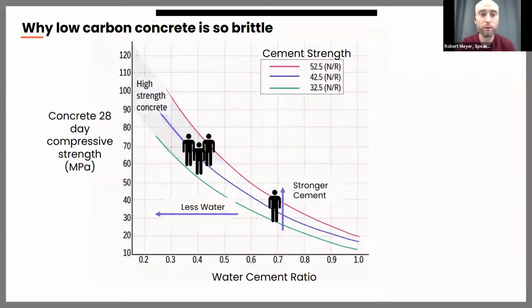Okay, so you might be wondering right now, okay, I can change the strength of my concrete either by cement or by less water. What has that to do with low carbon cement and low carbon concrete? Well, the hard truth here is that low carbon cement is basically made by replacing the clinker, which is this nice material that gives the strength, with filler material, so to speak. We actually have a very, very weak cement in our hands, meaning if I use low carbon cement and I want to get concrete strengths that are useful in everyday mass applications, so something between like 30 and 50 megapascals, I already have to operate in a very, very low water regime with like 0.35 or 0.4 water cement ratio.